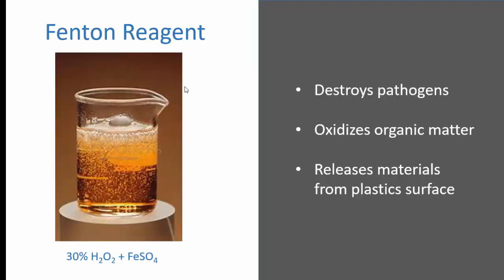We do this with a Fenton reagent, which is a 30% peroxide with an iron catalyst. This will destroy pathogens. It oxidizes the organic matter in the sample, rendering it much cleaner, especially in those effluent samples where you have a lot of algal material. And it also releases materials from the plastic surface.